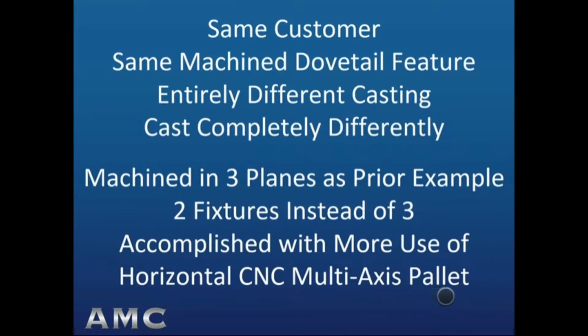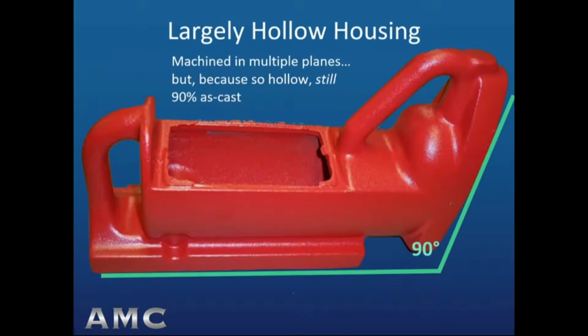Here's an overview of what the casting looks like. The photograph was taken with a wide-angle lens, and the vertical surface at the right-hand side really is at 90 degrees with respect to the bottom. The main point is the casting is hollow all through its center, and the hollow section extends into and through that 90-degree feature at the right. Even though the casting is machined in 3 planes, because it is so hollow, it is still 90% as cast in its finished net shape.